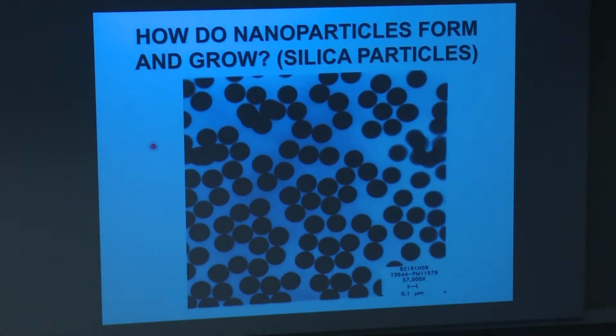And one of the questions that was asked is, how do these very monodisperse nanosilica particles form and grow? And there was a debate, one where one group said that very small particles, 1 to 2 nanometer particles formed, and then they would aggregate to form these very nice looking particles.